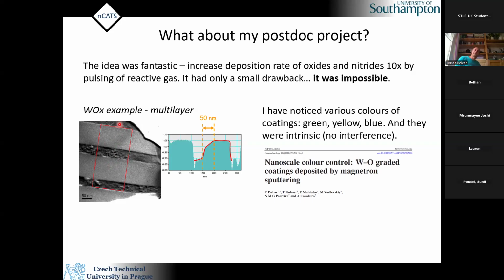But now I was thinking, look, what is really interesting for me is that this multi-layer structure has very nice colors, because we produced the coating and it was green. And we did another one with different conditions. It was yellow, and another one was beautifully blue. And I started really thinking, is it really interesting to have these coatings? Because they were intrinsic, it means there was no interference. When you change the angle or even the thickness, it was really the color of the coating.